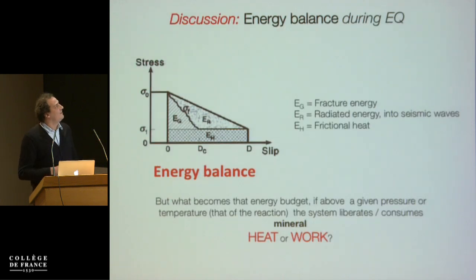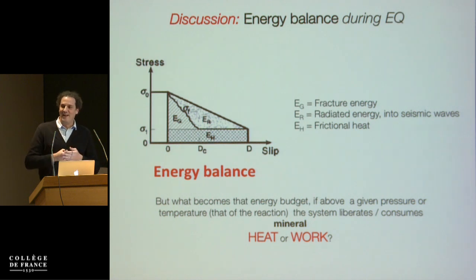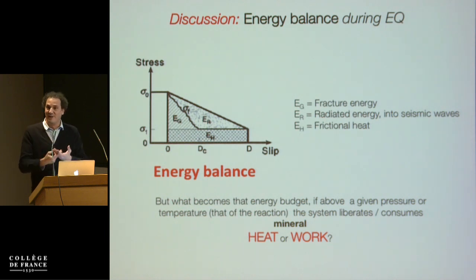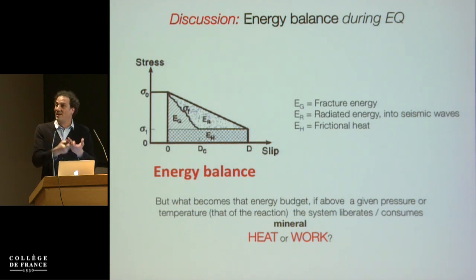And just to finish and discuss, these experiments tell us that we have this vision in our mind of the energy balance of the earthquake, of the earthquake fault, where you have the fracture energy, the radiated energy, and the heat. It's not that I think this balance is wrong. I just think that we always think that the fault plane doesn't contribute to the energy balance. And in fact, minerals have an enormous amount of potential heat in them because they transform, and the transformation can be endothermic or exothermic. They also have an amount of work in them because they can produce fluids or produce porosity, so they can reduce the pressure or increase the pressure. And so we need to try to find a way to incorporate this in our energy budget,